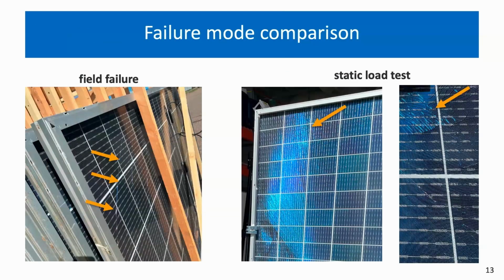However, if we compare this to field failure, and this is probably really hard to see, there's only a single crack here. I tried to highlight this with the arrows, versus this is what we're getting in the static load test. So our test setup doesn't really capture what's going on in the field. So we had to reassess our study and figure out what's actually going on in the field out there.